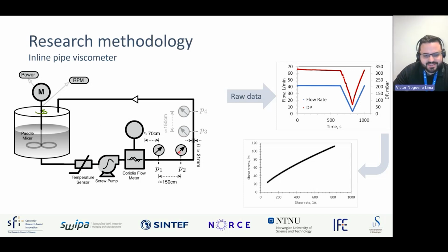So the setup is connected in parallel to a batch mixer, as you can see here, and it's used to run the sequences, where we can grab the raw data. The raw data is basically the one that we can see up here. That is the flow and the DP through time, and this flow rate and DP through time we can easily convert to shear stress and shear rate using some calculations.